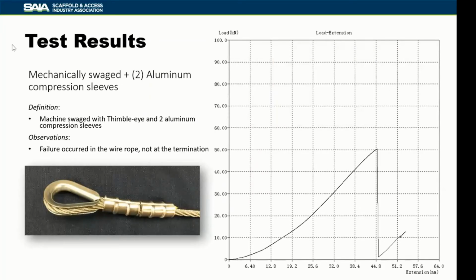When we go to the aluminum, we see very similar results to what we see with the copper-coated sleeves. Again, the extension is slightly more than what we saw with the copper compression sleeves, but not much more, about 1/4 inch more extension. We will talk a little more about aluminum sleeves because there are some recommendations by manufacturers of aluminum sleeves that even though we get performance that is acceptable, they may not be acceptable for use in lifting applications.